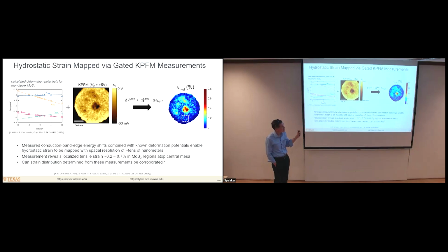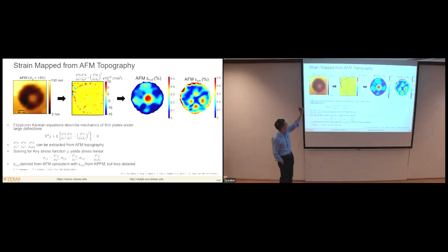Now, you might ask, okay, that was a pretty long path that we're following to get this. So is there some way that we can corroborate the strain distribution and see, does it really look like this? So there is another way that we can do this, which is that it's also possible to extract information about the strain from just the surface topography, which can be measured in conventional atomic force microscopy. Okay, so this is done basically by using tools from mechanical analysis of the deflection of thin plates. So the TMD layer is acting as the thin plate in this approach.